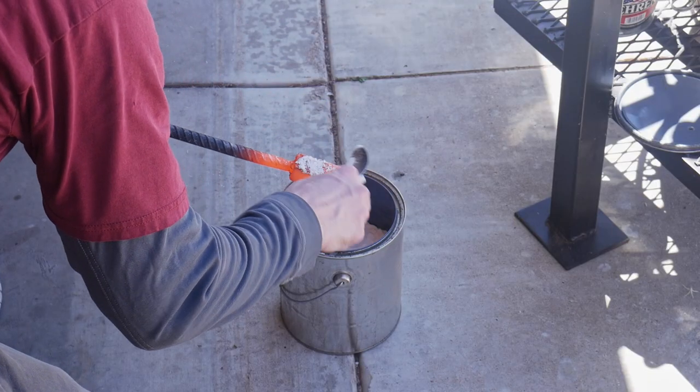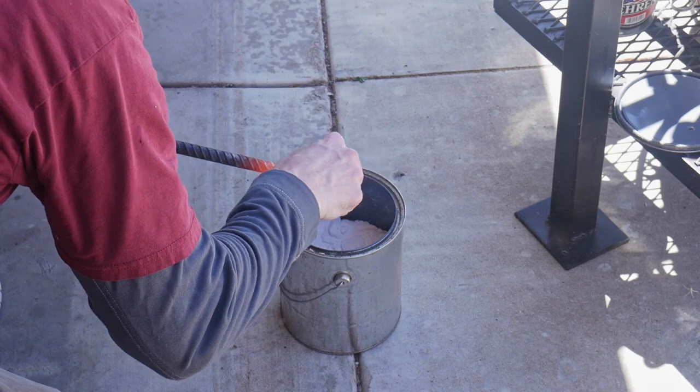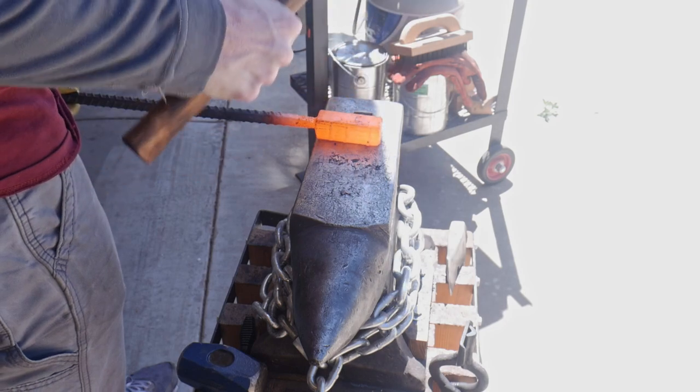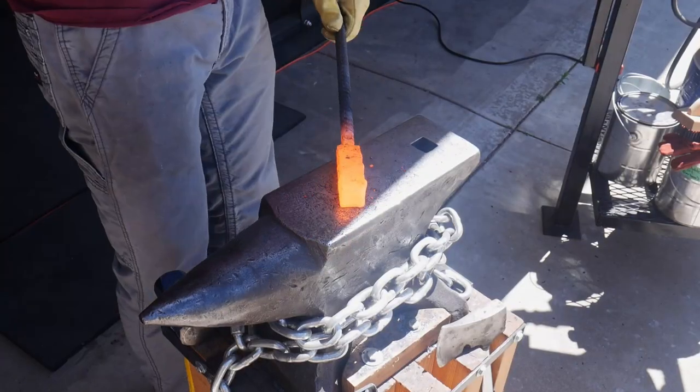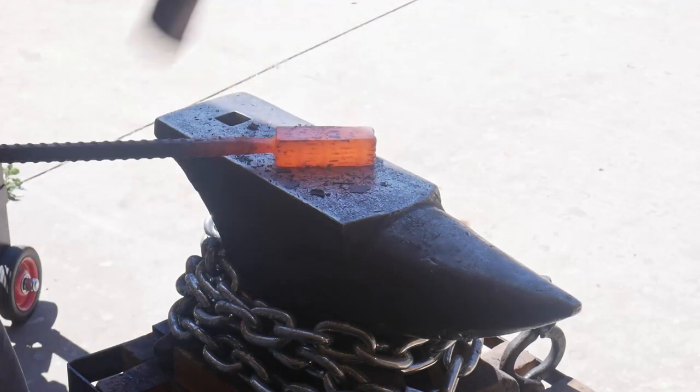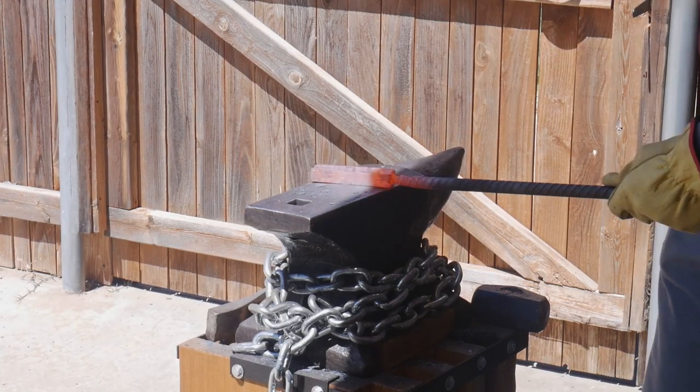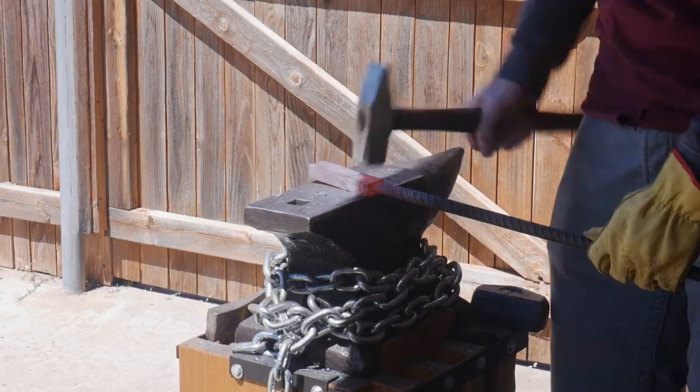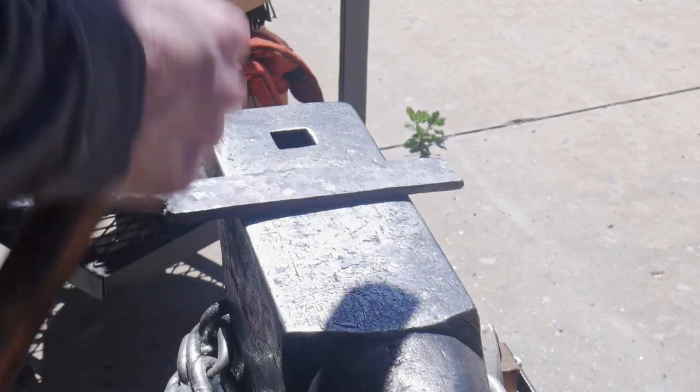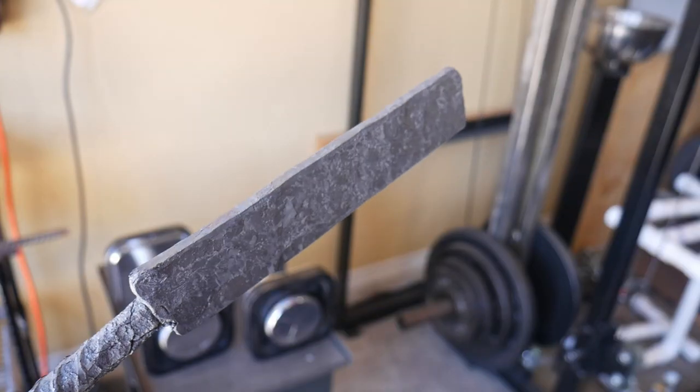On the way up to my welding heat, I take some borax and try to get it into all of the creases on the sides of the billet to prevent any oxidation in between layers. The first couple hammer strikes were very light and targeted to set the welds initially, and then I draw the billet out.